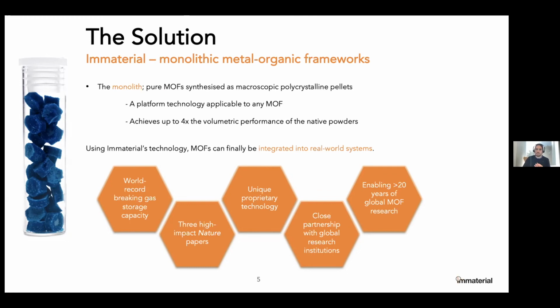One of the really important things about these pellets is you can get close or even all the way to the crystal density. A lot of the performance parameters reported in the literature are relative to these crystal densities. But in traditional pelletization techniques, you're often adding binder, or you need to compact them, and that can really destroy the properties of the metal organic frameworks. In contrast, this controlled crystallization process allows us to remove or tune the porosity profile and get to something which is essentially a pure crystalline pellet. And that means that in real world applications, we're seeing up to 4 times the volumetric performance of the native powders.